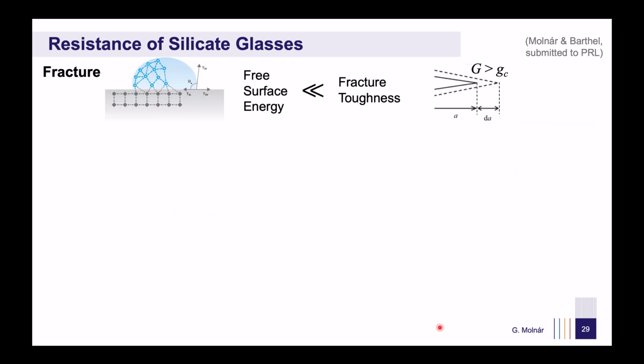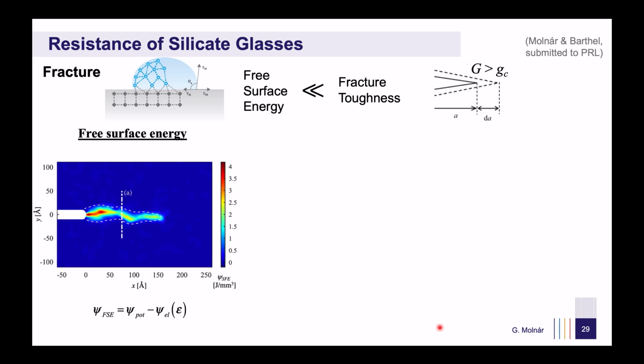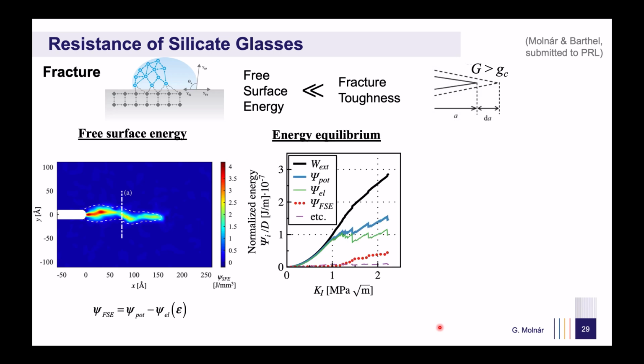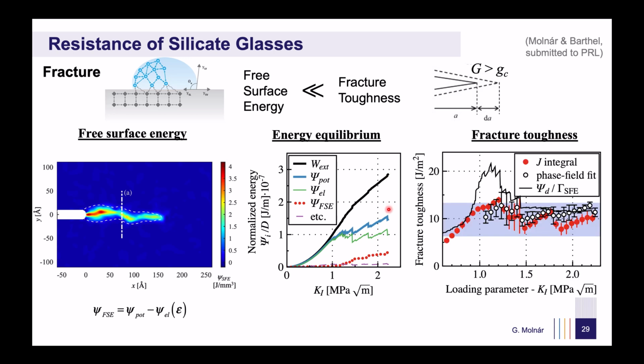With this information, we were able to distinguish between free and fracture surface energies. In theory, both quantities represent the energy required to create a new surface, but experimentally their values differ significantly. We showed that by subtracting the elastic energy from the coarse-grained potential energy, the free surface energy could be made visible. Examining the global energy balance, we confirmed that this free surface energy contributes only a fraction of the total energy dissipated. By using either the phase field fracture surface or the surface identified through the free surface energy, we obtain toughness values that align well with experimental measurements. This confirms that diffuse damage exists and that it is not plasticity but damage that establishes the correlation between free and fracture surface energies.